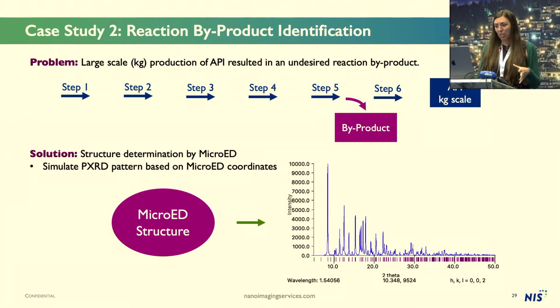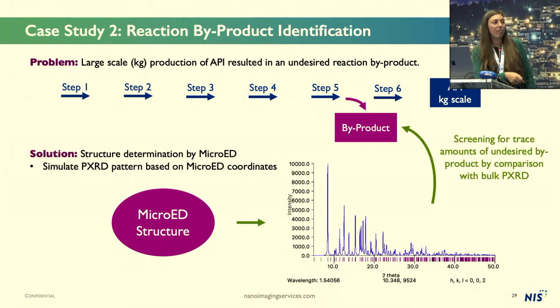Another great thing from this structure was that they were able to take our structure and simulate the powder diffraction pattern. And now they were able to use this as a kind of fingerprint. Every time they run step 5, they can collect a bulk powder diffraction and look for trace amounts of this unwanted impurity, and they can really identify if they're having a problem again. So this was a great success.